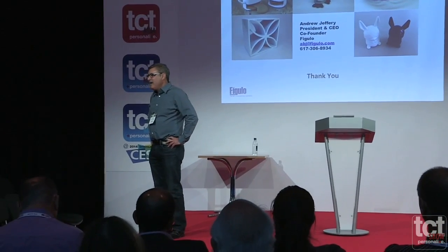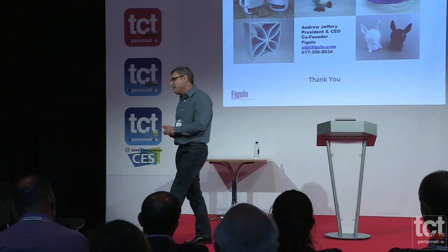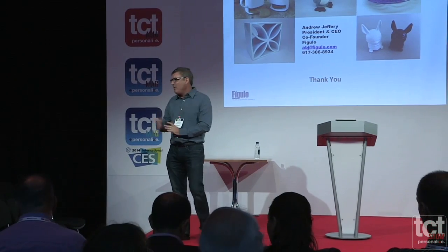What is your biggest build area at the moment? We're using a Z510, so we can do 340 millimeters by 240 by 200. But one of the things we can do, our material has some fairly unique properties in that we can make assemblies and fire the pieces together. So our real technical limitation in size is the size of our kilns. That really limits the size of the object that we can physically make, is how big we can fire. Our biggest kiln is about half a cubic metre in size, and I think the tallest we can go to is about 750 millimetres.